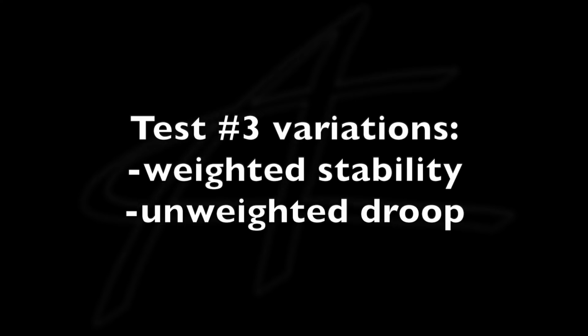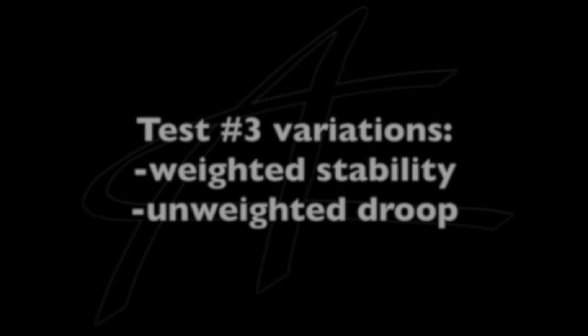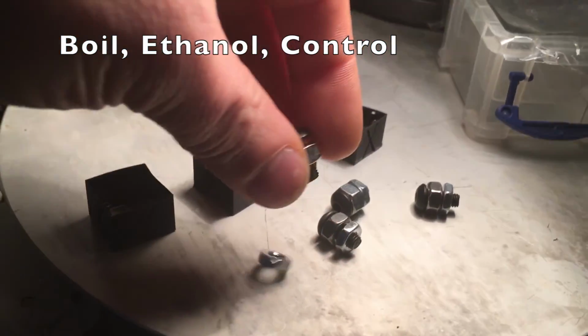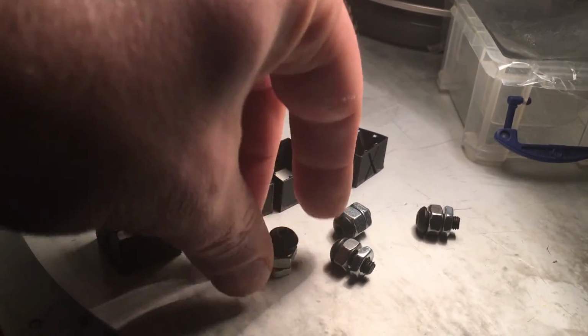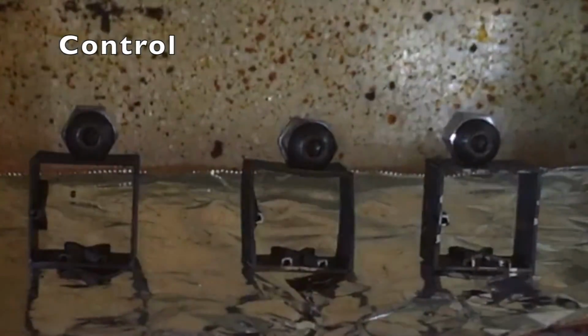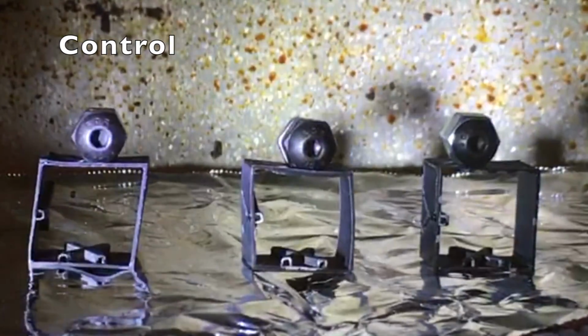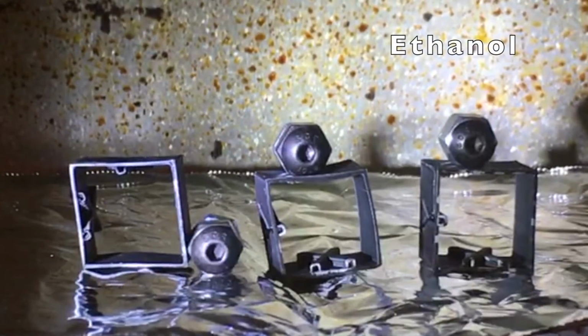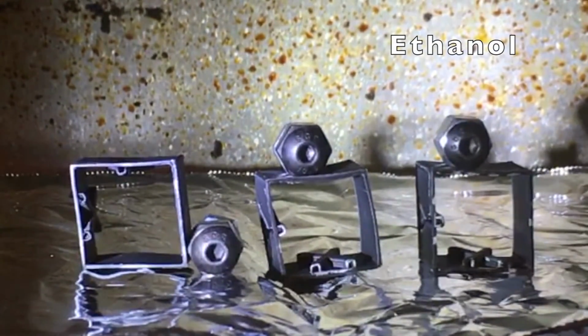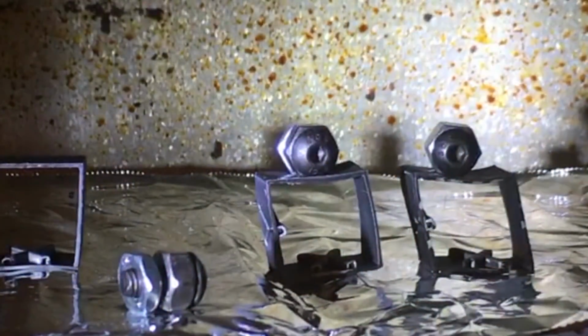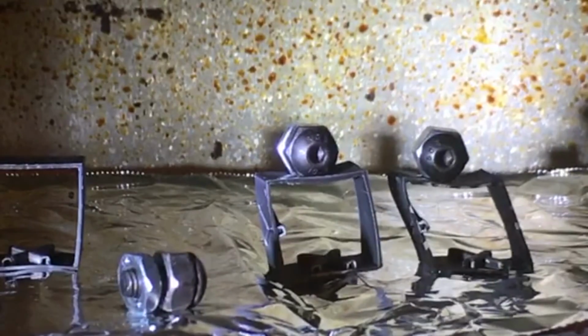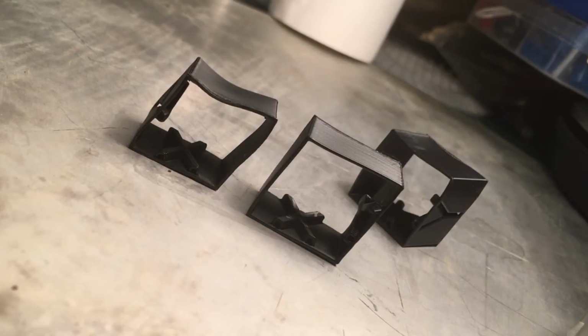For the next test, I decided to do the shell-only ringing test that I recycled from a previous experiment, and I did 2 variations. One weighted down with bolts so that I could see the structural integrity, and the other just to watch the droop as I turned up the temperature. So again, you can see right here, the control on the left almost immediately falls over, followed by the ethanol annealed on the right, which has much more structural integrity at higher temperature than the untreated does. And then in the middle, we have the boiled piece, which you can see is already a little deformed from the boiling, but deflects heat very, very well.